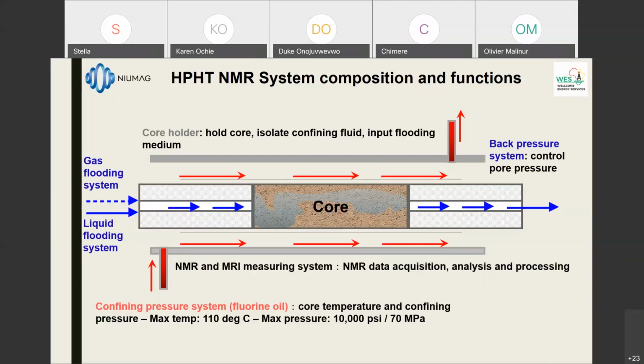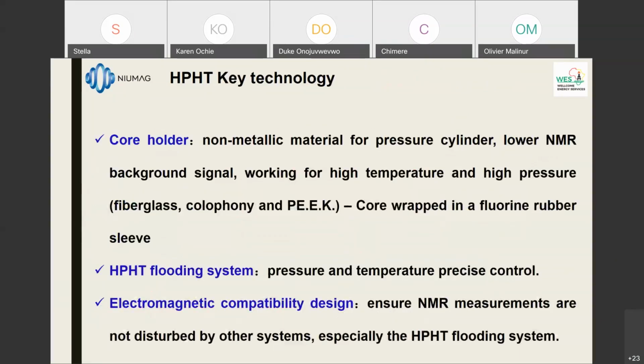Then you have the NMR and MRI measuring system to measure the whole. Now, the core holder itself is made of a non-metallic material because otherwise the NMR will not work. It has a very low NMR background signal. It's working at high pressure and high temperature. It's a mixture of fiberglass, colophony, and what we call PEEK, which is polyether ether ketone. It's a special material.